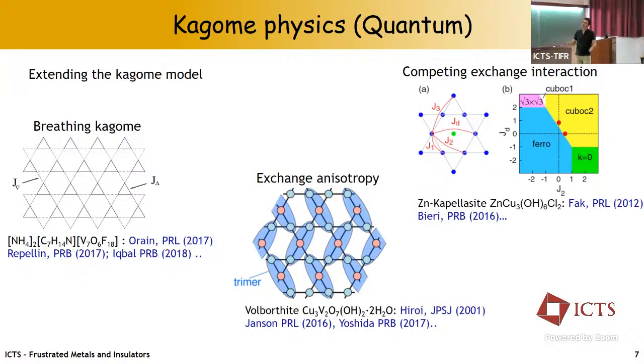You can think of adding further neighbor interactions, as was the case in this compound, Zn-Kapellasite, where it turned out that the first nearest neighbor was actually pretty small and even slightly ferromagnetic. And the other interactions are important, and they define a very large phase diagram with interesting phases like chiral phases, etc., which are still under investigation.